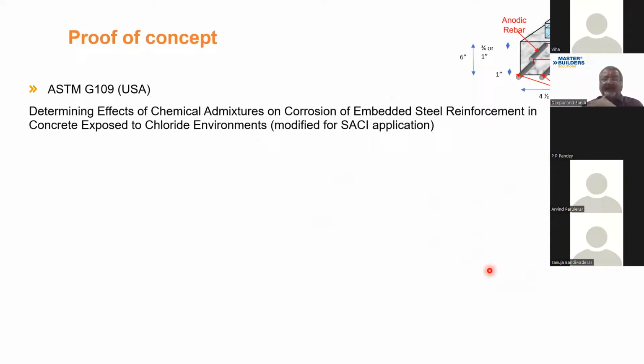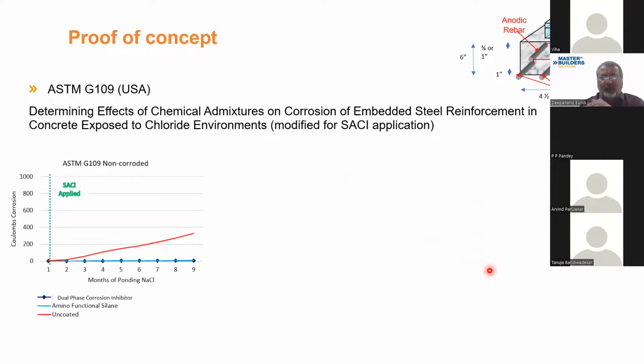I'm not sharing everything here, but the specific ones, as per ASTM G109: the specimens were coated with 2 different silane-based surface-applied corrosion inhibitors. On the left graph, the specimens had been cast and cured before application of the 2 different surface-applied corrosion inhibitors. The one in blue is the dual phase corrosion inhibitor, and the red one is the uncoated. In terms of the coulombs passing, it is almost 0. So there is no corrosion activity that you can see in the graph.